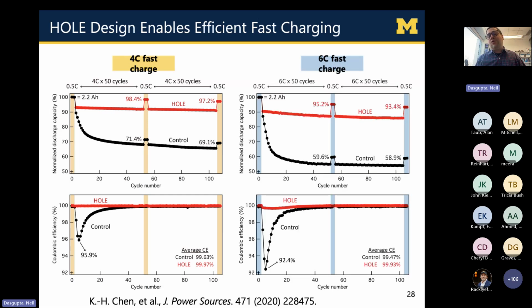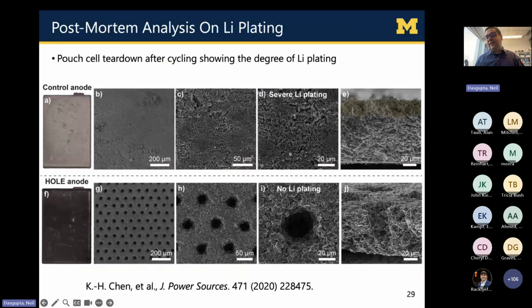The differences are even more dramatic if you push the battery harder to a 6C rate, which again is a 10-minute recharging time. You can see at 6C, the control electrodes lose 40% of their accessible capacity, whereas the hole electrodes still maintain over 93%, with no evidence of this dip in coulombic efficiency, which indicates lithium plating.